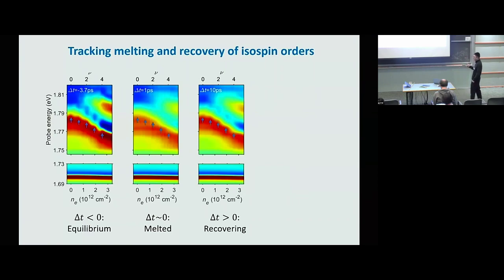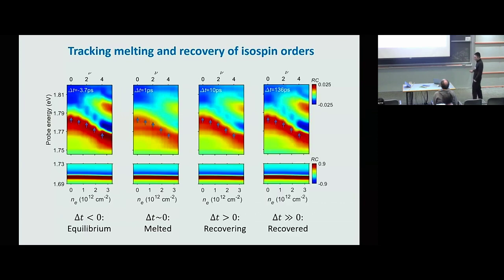start to recover. They are not fully recovered yet, but they are recovering. And if we wait a little bit more, at a few hundred picoseconds, it's almost recovered, approaching equilibrium again. So from this snapshot, we can get a quick glimpse of the excitation process and the relaxation process. Our goal here is to look at the relaxation dynamics of the isospin fluctuations or excitations. So let's take a look at the relaxation process more quantitatively.